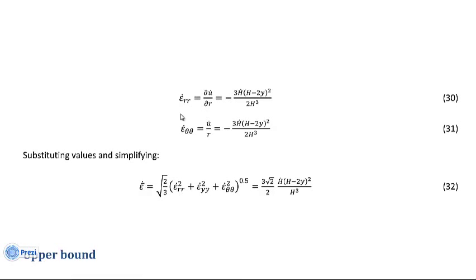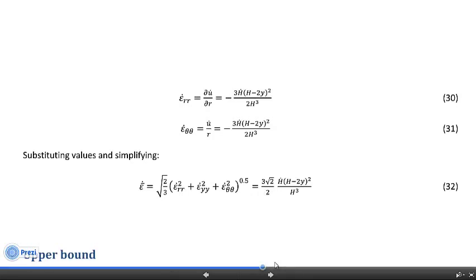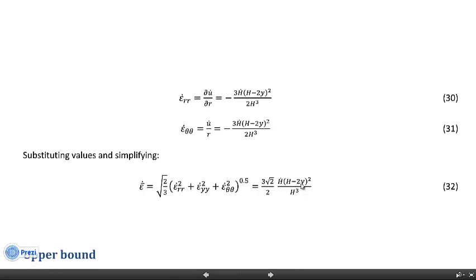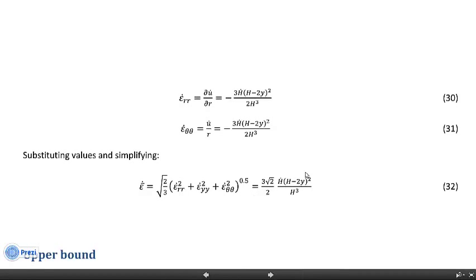Now that we know u-dot, the two other normal strain rate components are both quadratic and identical. Plugging these into the definition of effective strain rate, an interesting observation emerges: contrary to the conventional solution, the strain rate is a function of distance from the coordinate system — it is not uniformly distributed throughout the sample. Comparing to finite element solutions, this is a more realistic assumption.